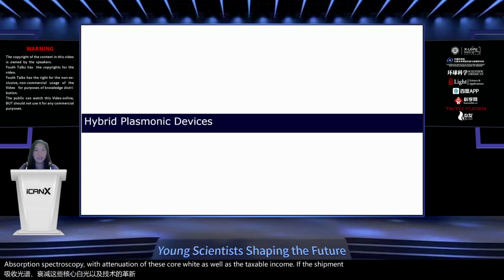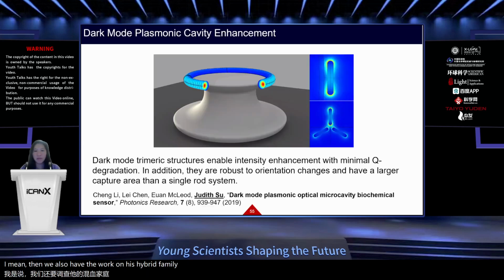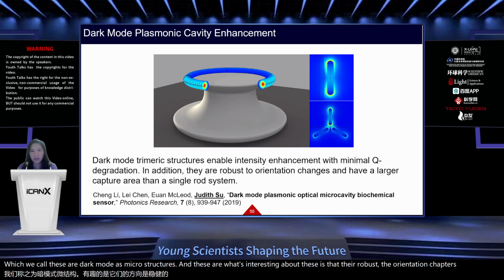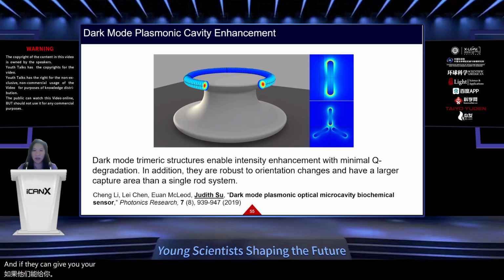And then we also do work on these hybrid plasmonic devices. People have coupled these devices with plasmonic devices because, for example, these gold nanorods can generate sensing hotspots at the ends of the nanorods. And what we've done, through simulation, is generate these trimeric structures, which we call dark mode plasmonic structures. What's interesting about these is that they're robust to orientation changes, and they can give you intensity enhancement, while you have minimal Q degradation because you're reducing scattering.